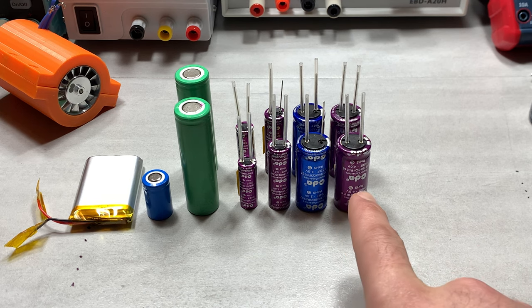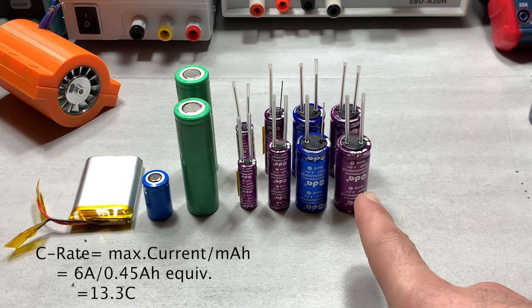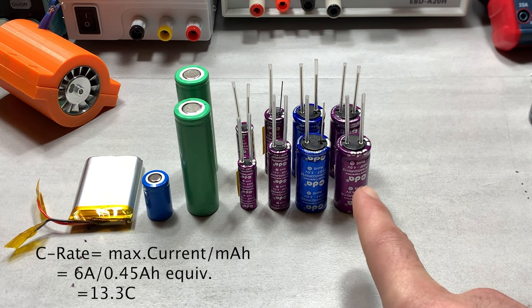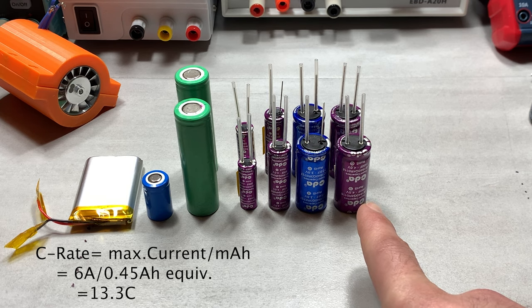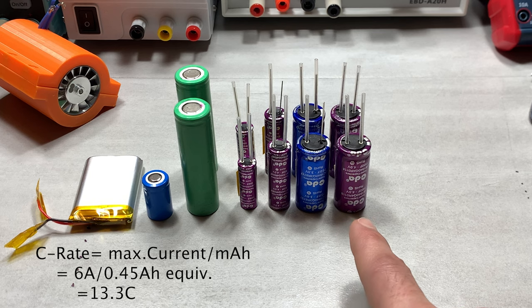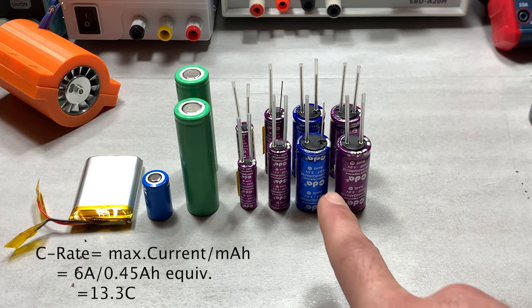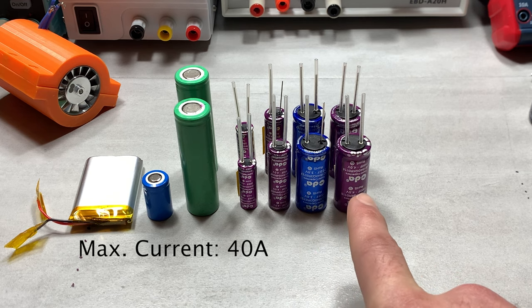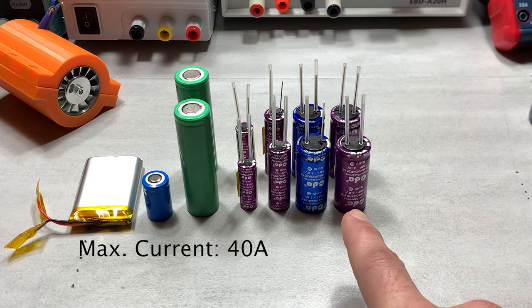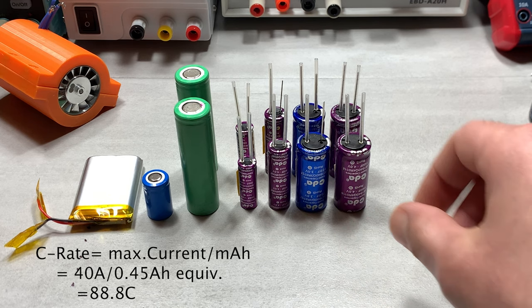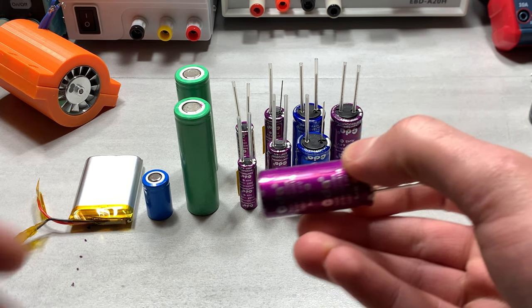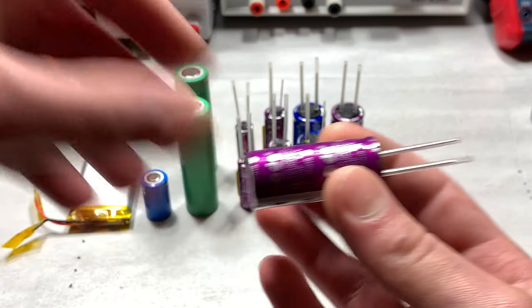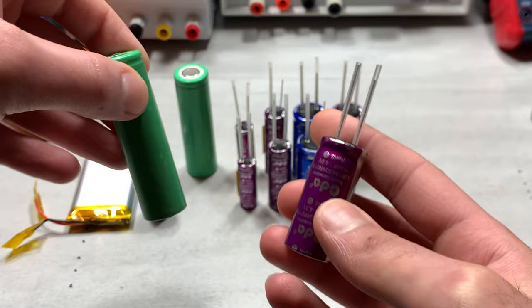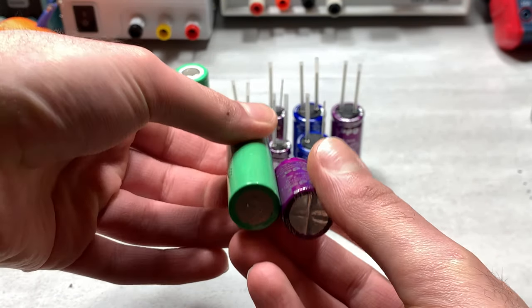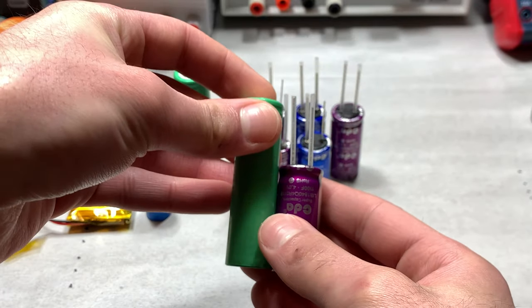So back to what the C rating would be for this. This is a 450 milliamp hour equivalent supercapacitor with a recommended current discharge rating of 6 amps. So dividing 6 by 0.45 amps gives us a C rating of 13.3 C, so 3 C above this one. But then the maximum current rating, which is a whopping 40 amps, gives us a C rating of 88.8 C for this tiny little cell. And I know I say tiny, but that amount of current, 40 amps from something this small, just putting that beside an 18650, that is mind-blowing.